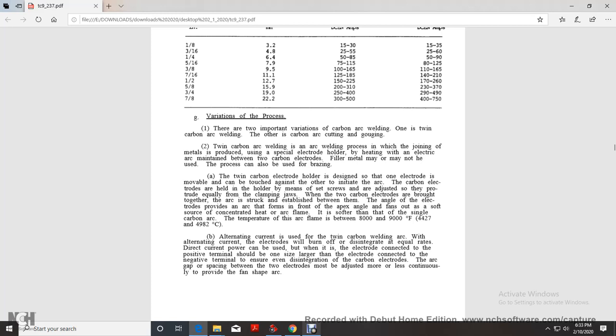The twin carbon electrode holder is designed so that one electrode is movable and can be touched against the other to initiate the arc. The carbon electrodes are held in the holder by set screws that are adjusted so that they protrude equally from the clamping jaws, and the two carbon electrodes are brought together. The arc is struck and established between them. The angle of the electrodes provides an arc that forms at the apex angle and fans out, giving a softer, more concentrated heat than the single carbon arc. The temperature of this arc flame is between 8,000 and 9,000 degrees Fahrenheit.